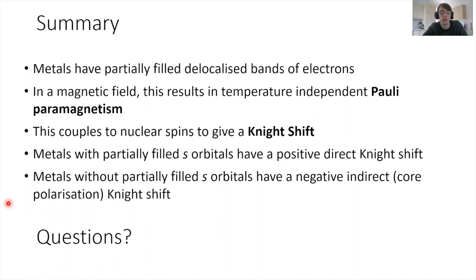The other contribution you can have is dipolar coupling between your nuclear spin and your electron rather than Fermi contact. That results in anisotropy, but it tends to actually be pretty small. The dipolar coupling with the delocalized electrons is comparably small, and so you end up with an anisotropy that is not as big as, for example, in localized paramagnetic systems with paramagnetic shifts that can be very anisotropic.